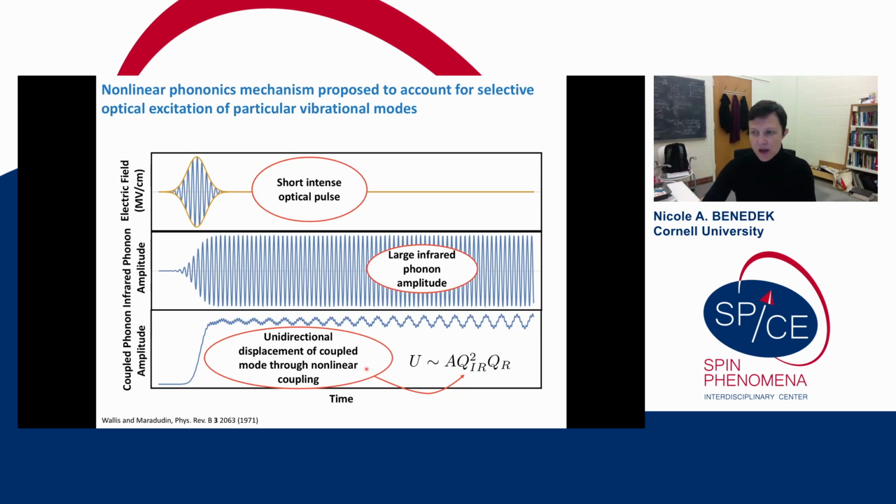The IR active modes are coupled to other modes in the material in a way that depends on crystallographic symmetry. And because this coupling exists, the ringing IR mode creates a force on modes that it's coupled to so that they also displace. And this displacement of atoms can change the properties of the material. So in the early nonlinear phononics work of the modern era, the specific coupling term that has probably been most well investigated looks like this cubic term.